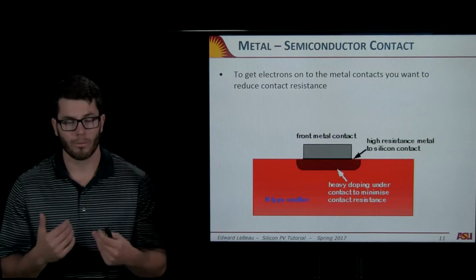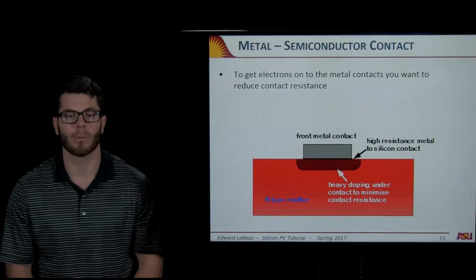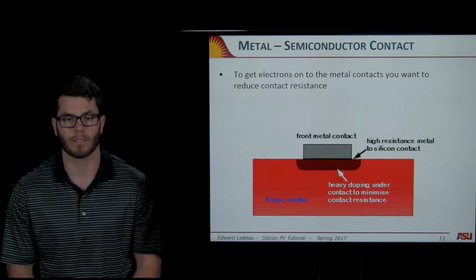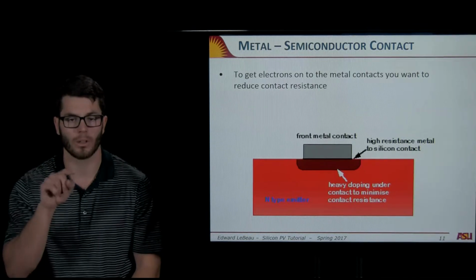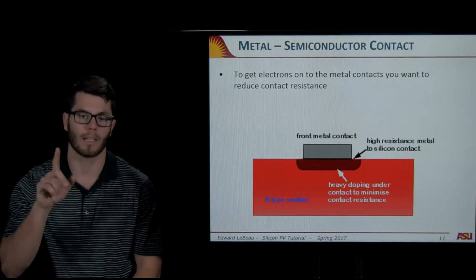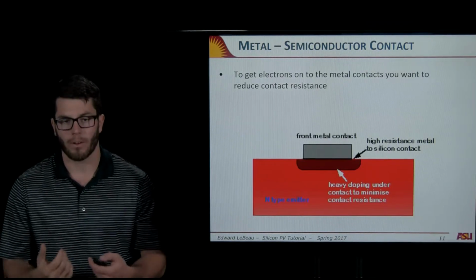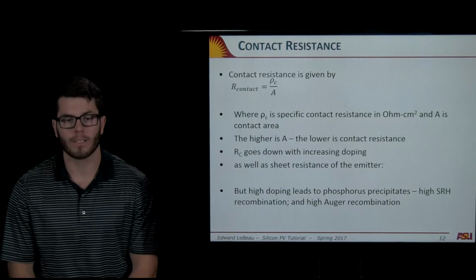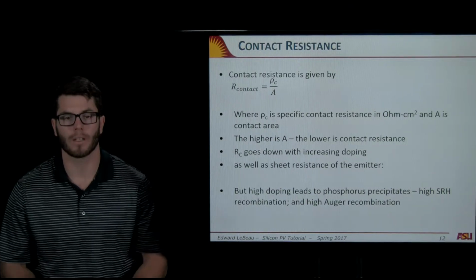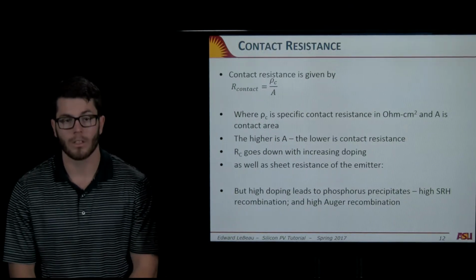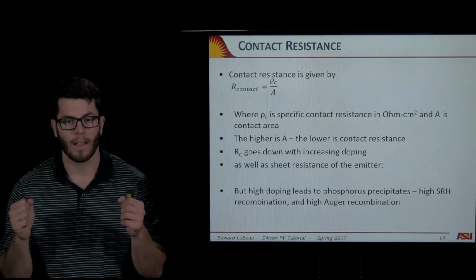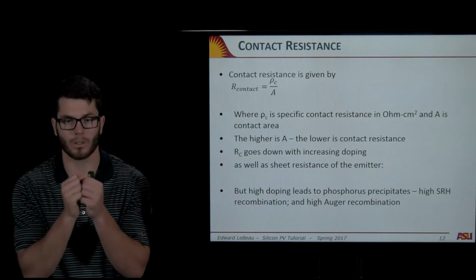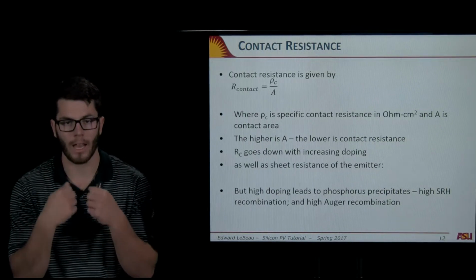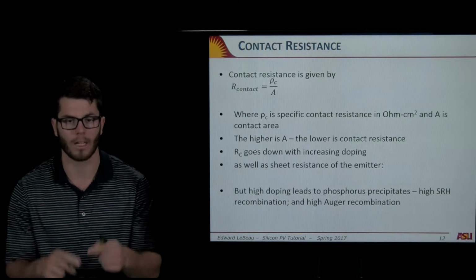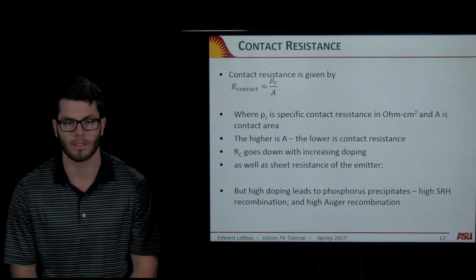Another series resistance that we mentioned earlier was the contact resistance. That's basically the resistance between your N-type emitter and your contact. So you want that to be very low. Your contact resistance is given by your specific contact resistance, which is an innate factor of the two materials you're putting together, and then A, your area. So if you have a big area of contact, you have a lower contact resistance.